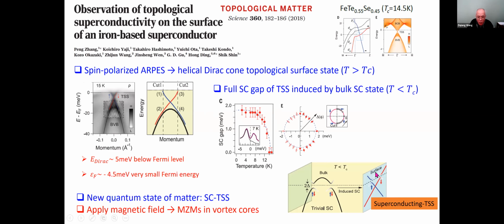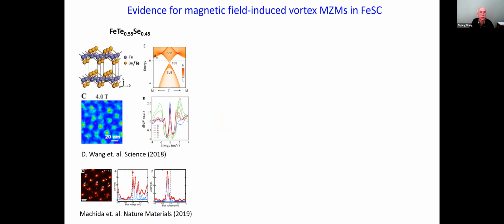Once again, this is not a topological superconductor. My experimental colleagues are very excited and wanting to call this thing a topological superconductor. It might be in some higher order categories, higher order definitions, but not in the conventional sense. But nevertheless, our discussion tells us if we apply a magnetic field, we should see Majorana zero mode in the vortex core because of these superconducting topological surface states. And that indeed has been found. In FTS, you see the zero energy bound state, and that is a candidate Majorana zero mode.